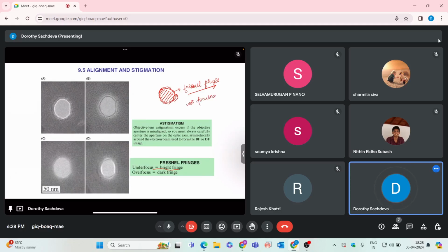So if it is under focus, then you will have bright fringes, and if it is over focused, then you will have dark fringes. And astigmatism, objective lens astigmatism occurs if the objective aperture is misaligned. So you must carefully center the aperture on the optic axis symmetrically around the electron beam to form the bright field or dark field image.